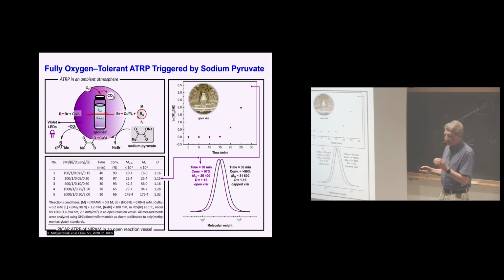You need violet light to activate this system. And you could see it takes 15 minutes to purge this oxygen by itself, because you have oxygen concentration sufficiently high. Then polymerization starts, and you could see open vial, 30 minutes, and this capped vial, 30 minutes, very similar results. So this is nice.